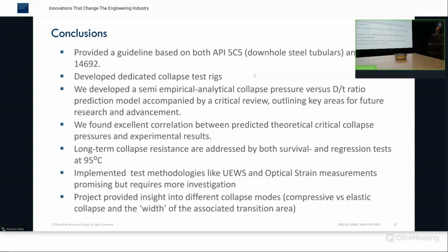So then, the conclusions. The main objective was to provide a guideline based on API 5C5 and ISO 14692, and I think we succeeded in that. We developed dedicated collapse test rigs, and a lot of knowledge has been gained from these tests. We developed a semi-empirical analytical collapse pressure versus D over T prediction model. We found an excellent correlation between the predicted theoretical critical collapse pressure and the experimental results. The long-term collapse resistance is addressed by both survival and regression tests.